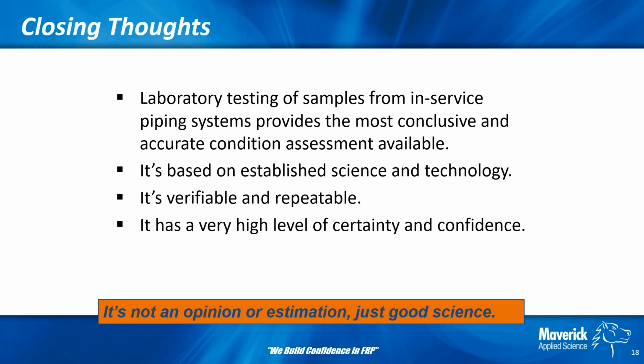We can examine it, we can cut it up, we can do all the scans and everything else that we need to do, and we can give them a real good assessment of the condition of the pipe, far more than what we can actually do even with our in-field inspections during outages. And they've done this more or less while they're in operation, with little to no interruptions, and they're getting a verifiable and repeatable result that we put in the form of a technical report. And it gives them a high level of certainty and confidence.